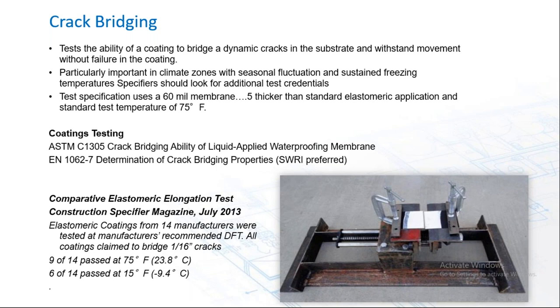But I think it's important here to reference the Construction Specifier magazine article back in July 2013, where they actually assessed the performance claims of 14 manufacturers with their elastomeric coatings that said they all passed at recommended dry film thicknesses. They ran a subsequent test and found that really only 9 of the 14 passed at 75 degrees, and even fewer passed at freezing temperatures. So there are test biases, I have no doubt, but there is also test execution bias as well.